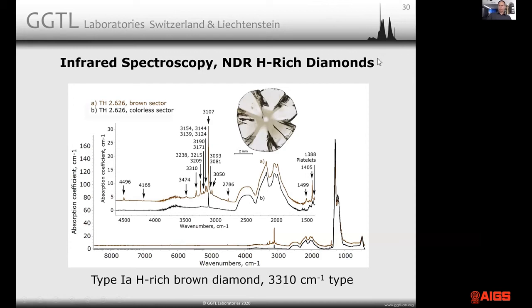The spectrum of the colorless sector can be seen as spectrum B, and the brown sector is spectrum A. Spectrum B barely contains any hydrogen compared to spectrum A. It's still hydrogen rich, but compared to spectrum A, very little. And all the cuboid growth related peaks are absent. This is a very thin plate, and that's why we were able to resolve the entire nitrogen absorption with a humongous absorption coefficient of about 170 centimeter minus 1.